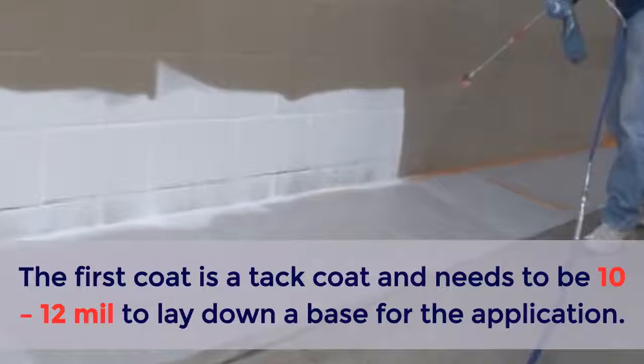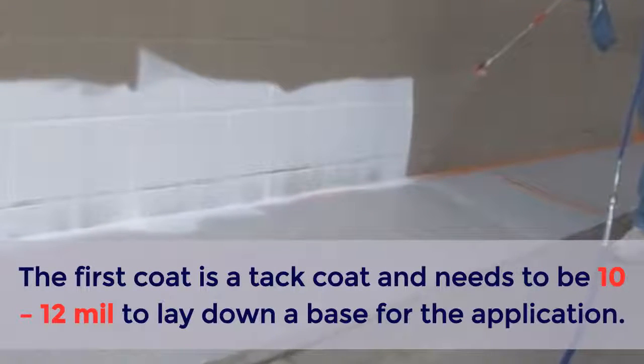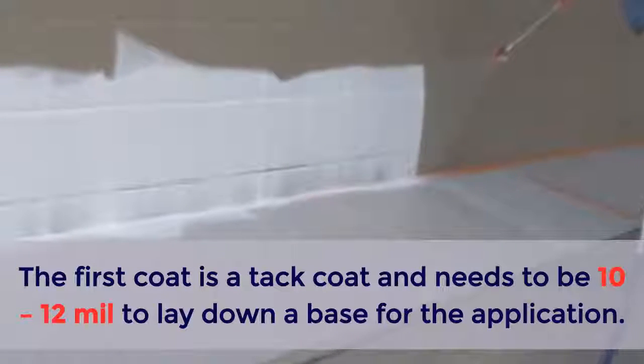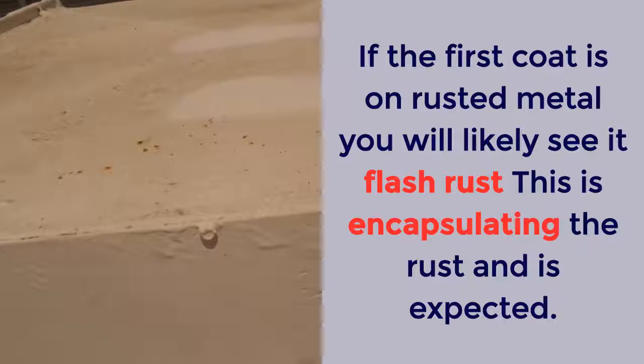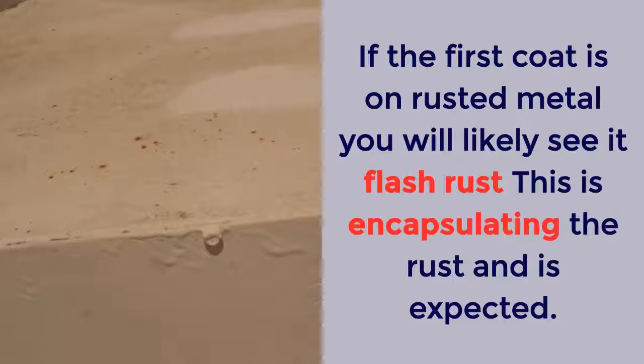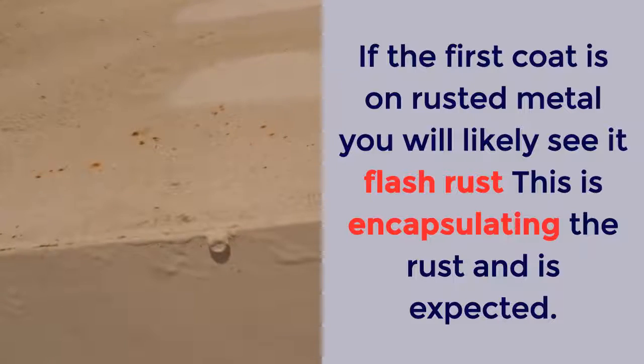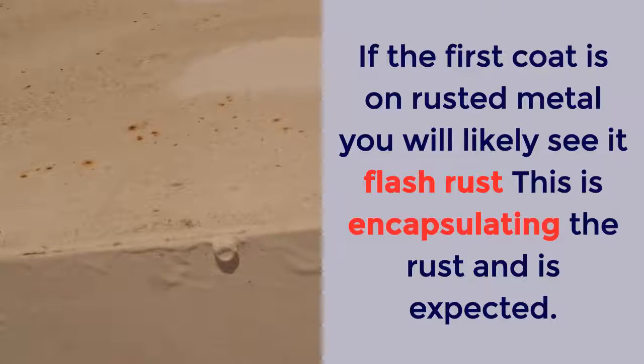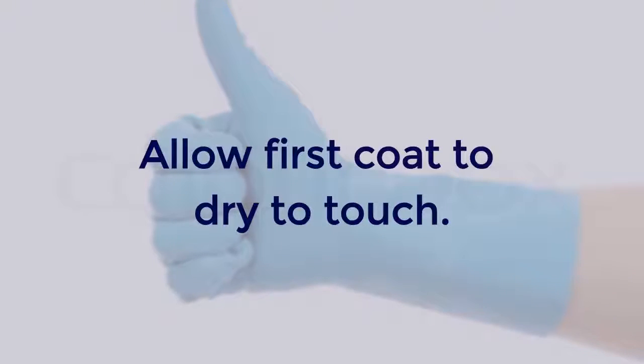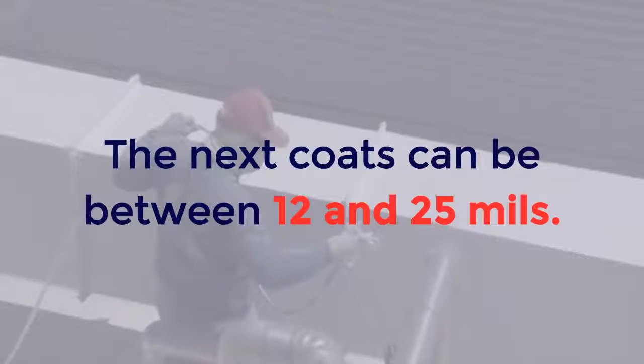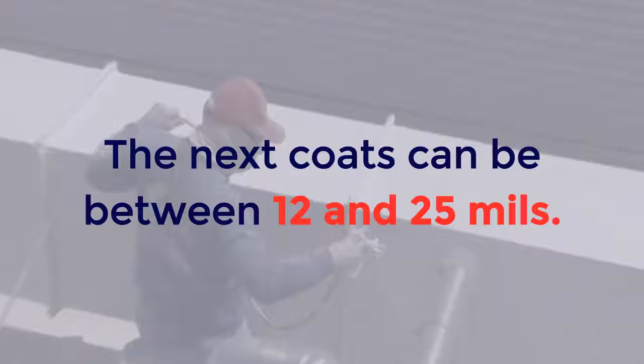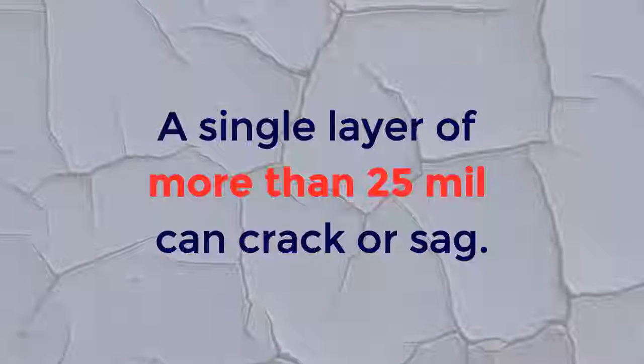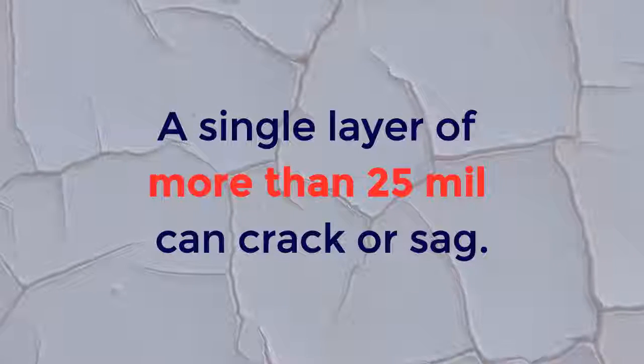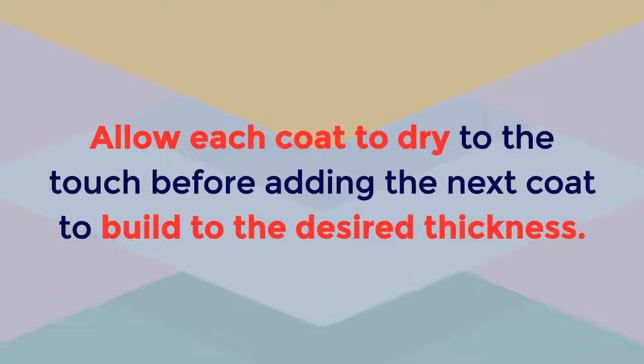The first coat is a tack coat. It needs to be between 10 and 12 mils to lay down a base for the application. If the first coat is on rusted metal, you will likely see it flash rust. This is encapsulating the rust and is expected. Allow first coat to dry to the touch. The next coats can be between 12 and 25 mils. A single layer of more than 25 mils can crack or sag. Allow each coat to dry to the touch before adding the next coat to build to the desired thickness.